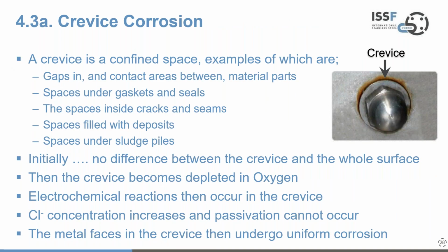So I'd now like to move on to crevice corrosion, which is quite easy to define but is often a surprise for people, because crevices in this domain are not always perceived as crevices. So I'll start with the definition. A crevice is a confined space, examples of which are gaps in and contact areas between material parts, spaces under gaskets and seals, the space or spaces inside cracks and seams, space filled with deposits or spaces under sludge piles. And the photograph on the right shows a crevice, which is actually the space between a washer and the material that it is fixing to something else. And perhaps you wouldn't normally consider that as a crevice, but it really is in this case. And you can see the corrosion occurring that sort of leached out from the crevice area.